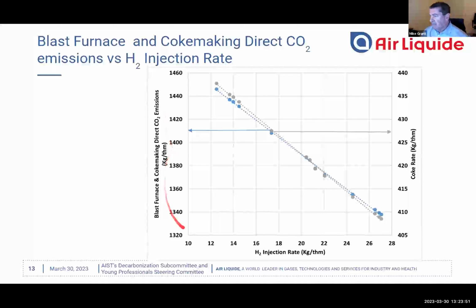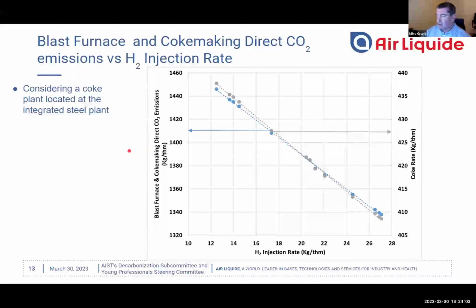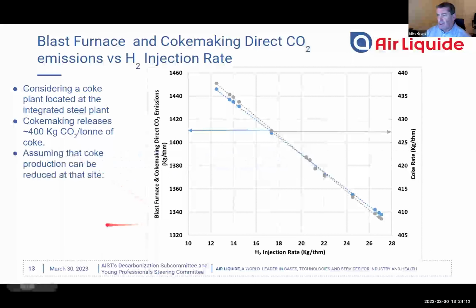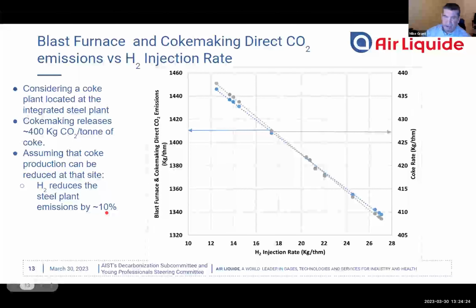Like the PCI graph, when we inject more hydrogen, we reduce our blast furnace and coke making direct CO2 emissions. Using the same assumptions that the coke plant is located at an integrated steel plant, with the same emissions for making coke, and assuming that we can reduce the coke production, we can get a small decrease in CO2 emissions from injecting hydrogen. And this is about 10%. And it's not very much. The blast furnace emits about 1.5 tons of CO2 per ton of iron that it makes. So if we are able to reduce 10%, that's only about 150 kilograms. And this, of course, is not really going to be acceptable for contributing to energy transition.